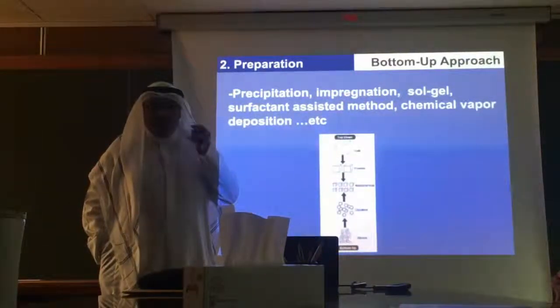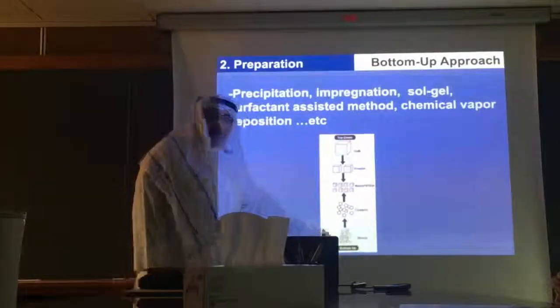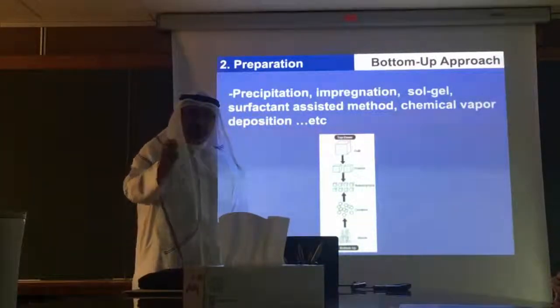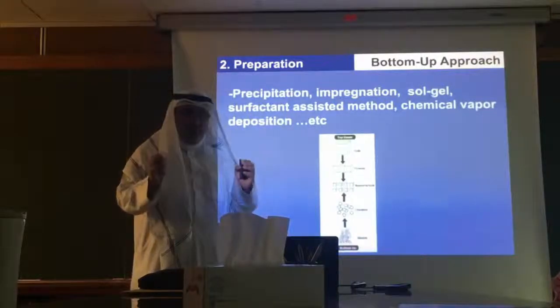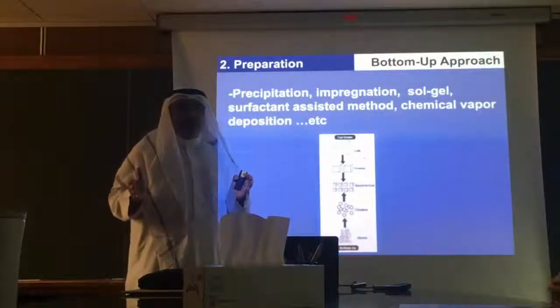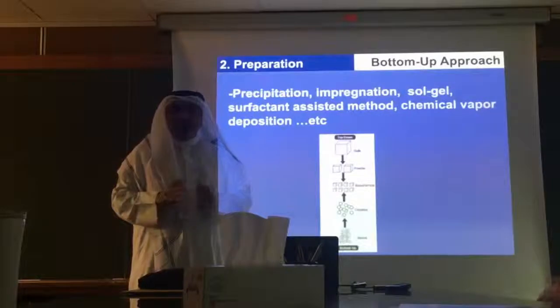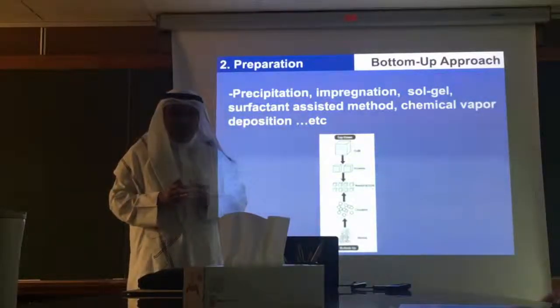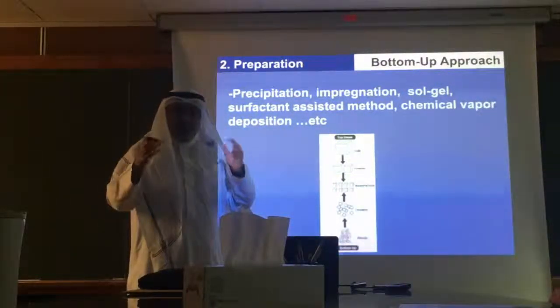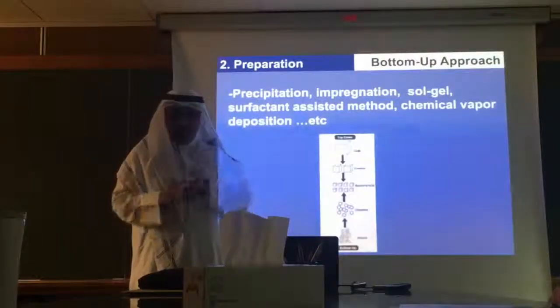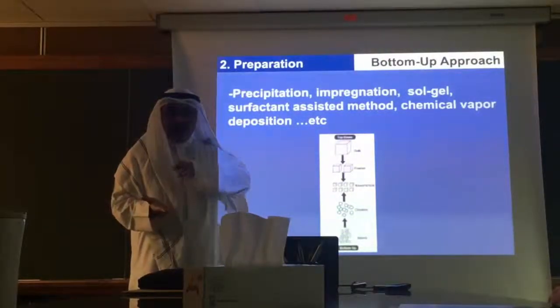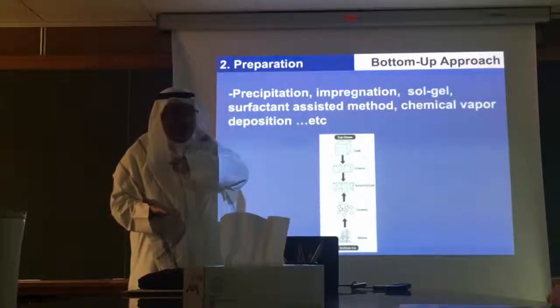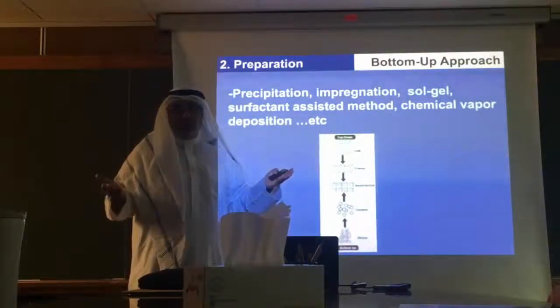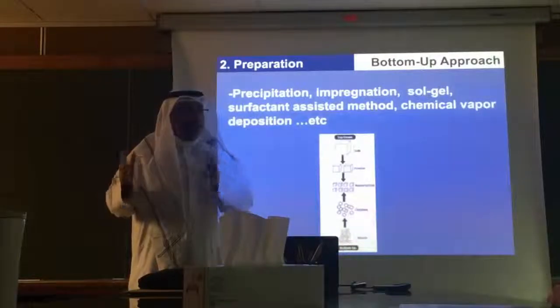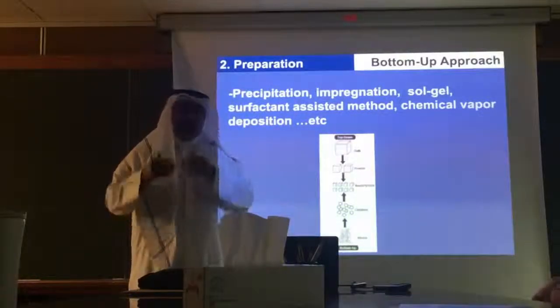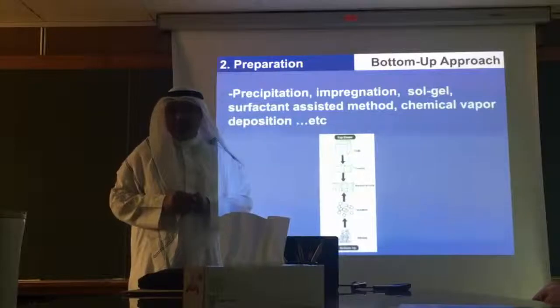But usually, you have to consider the process called nucleation and growth. So you start with the nucleus, very small particles, and then it will start to grow. You have to control the kinetics of this process. You have to make all the nucleation start at the same time, and then stop, and then start the growth. If some particles start nucleation at an early stage, and another particle starts nucleation at a later stage, this will give you polydispersed particles. You have to control the kinetics. For example, 5 seconds of nucleation, and after 5 seconds the growth can start.